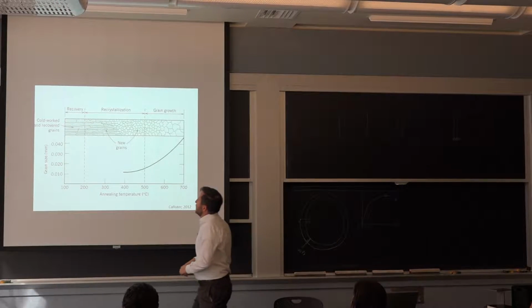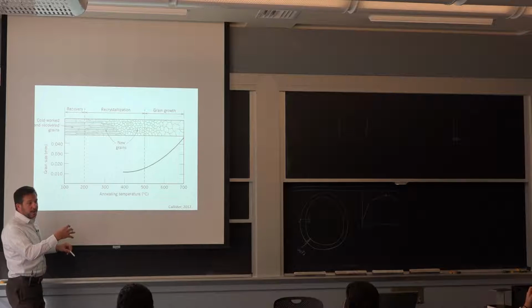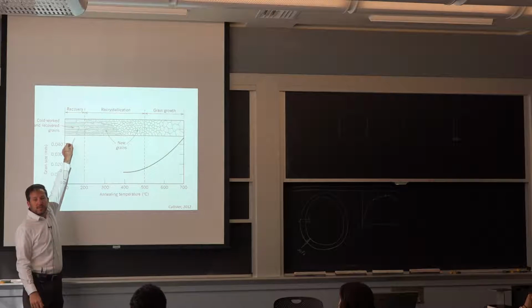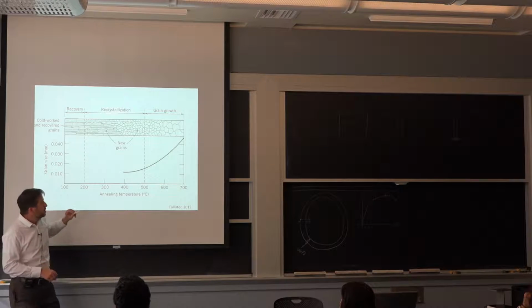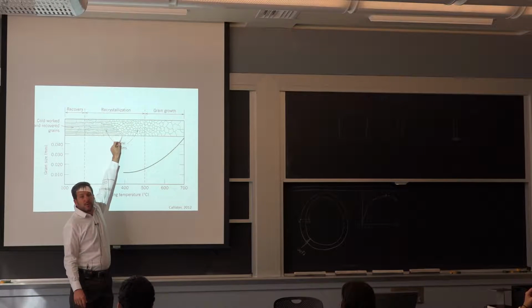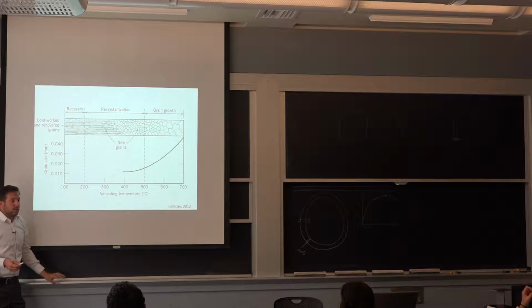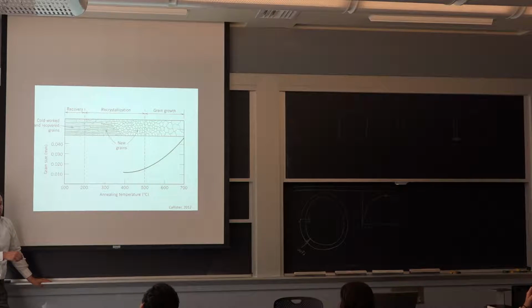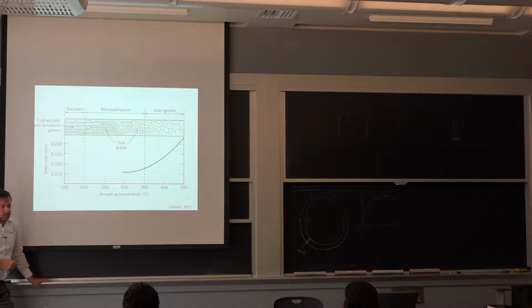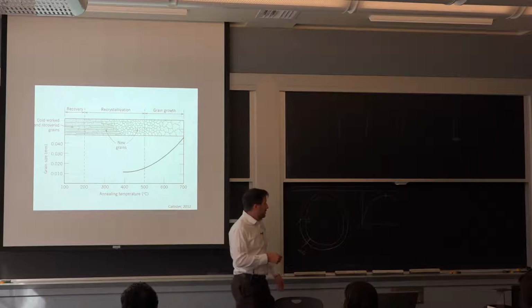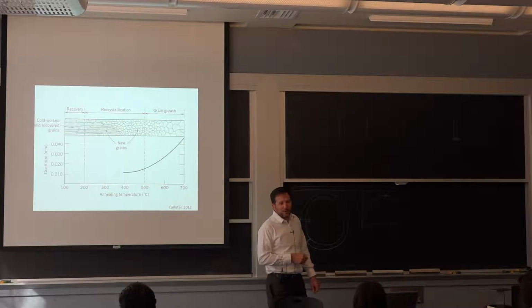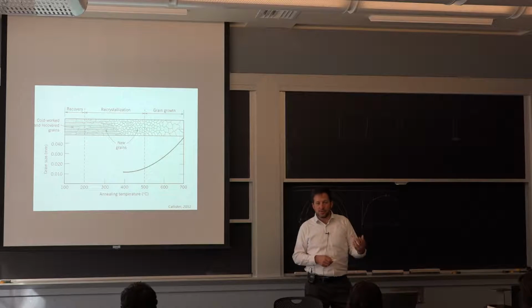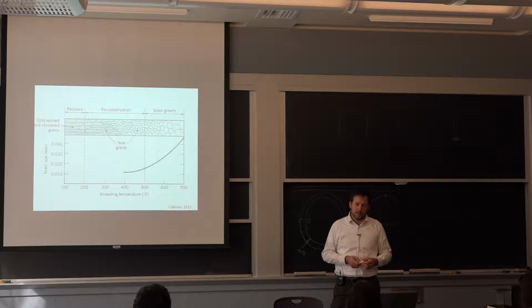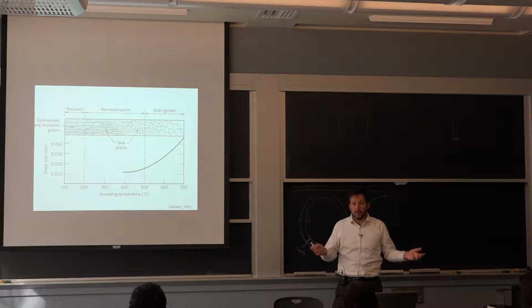So at the center, if we magnify in on that pipe, we see the elongated grains, and they're bigger. On the surface, we see smaller grains that are almost equiaxed. So essentially, the surface of that pipe recrystallized, but not the core, because it didn't have as much internal energy in the grains. Overall, it means it's a lot more difficult to take a surface measurement and go to the core, because now you don't have just a strain, you have a different microstructure to deal with that's going to have a different hardening behavior and a lot of other characteristics.